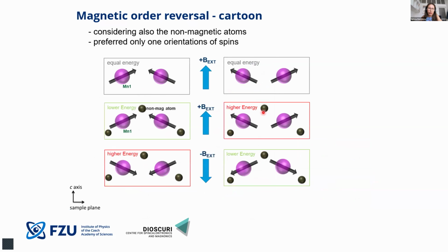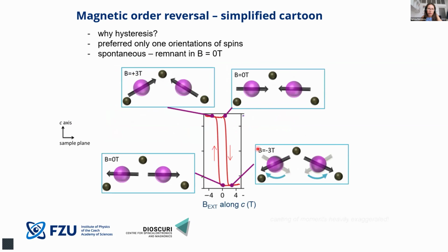However, once we consider also the non-magnetic environment in the simplified case, we can clearly see the difference between these two, and one can attribute schematically that one of them has lower energy and one of them has higher energy. And then when one shows this reversal curve, in the high saturated field, this is the preferred, the low energy configuration.